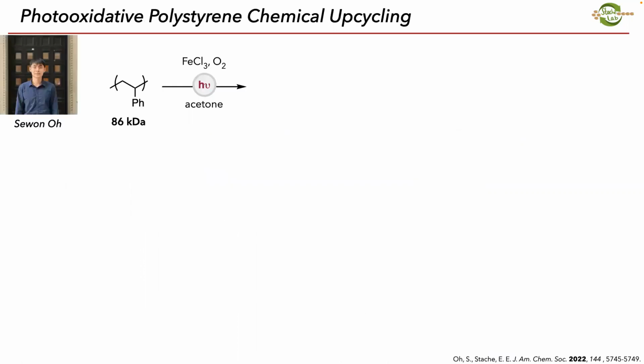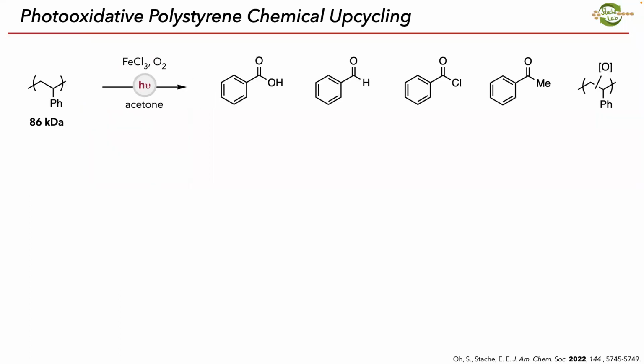So this is work done by a graduate student, Sewon. He took a lab synthesized sample of polystyrene. So 86 kilodaltons is essentially the size of this polymer. He exposed it to iron trichloride in the presence of oxygen, visible light, and in acetone, which is a very cheap solvent, and then detected all of these different oxidized aromatic products in a GC chromatogram, and then also observed this oxidized polystyrene or styrene oligomers.